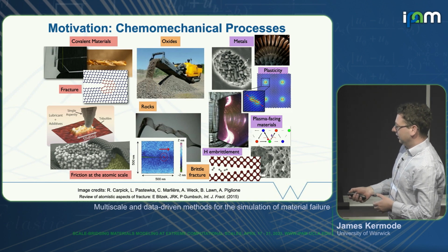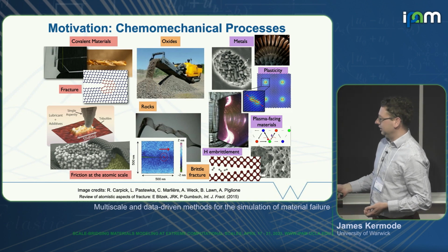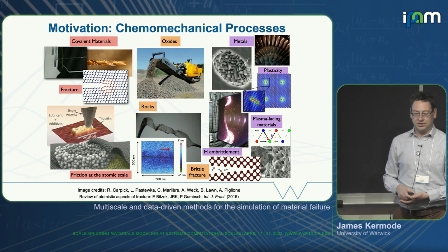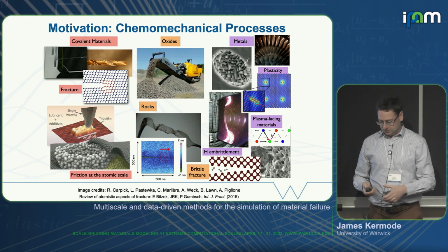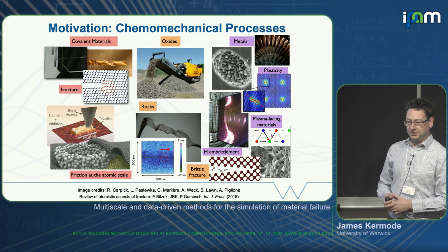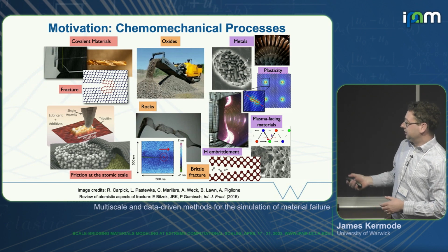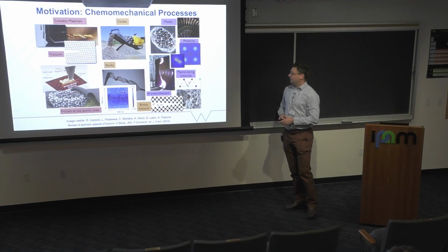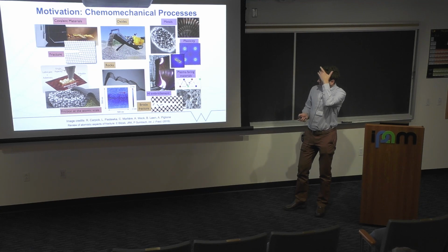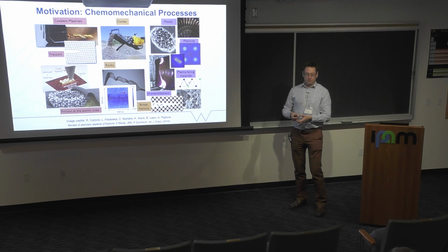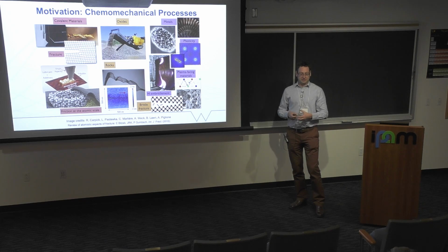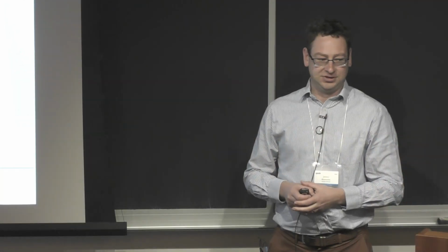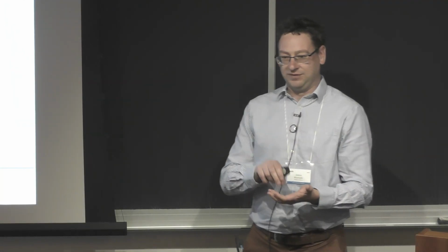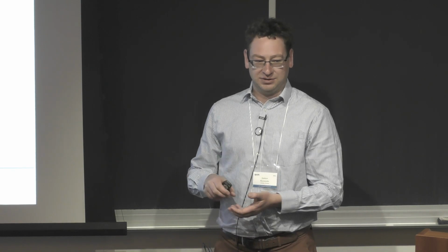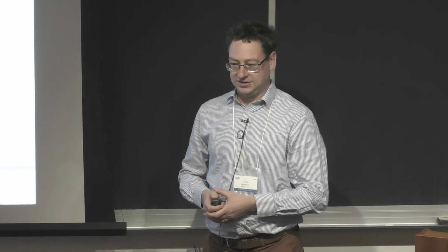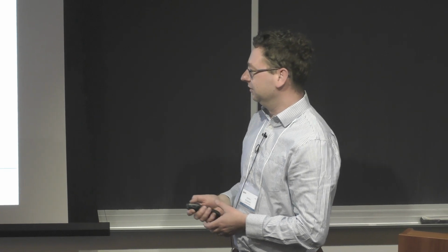Other examples include friction. So this is an AFM tip sliding on a surface. Again, local rearrangement of chemistry, but long-range interaction and strong coupling with stress. Or plasticity. This is a super-alloyed turbine blade for a jet aircraft, which is a single crystal of nickel with nickel-aluminium precipitates, and we're interested in engineering the material to control the plasticity response to prevent dislocations from entering these precipitates and adversely affecting the ductile response of the material.